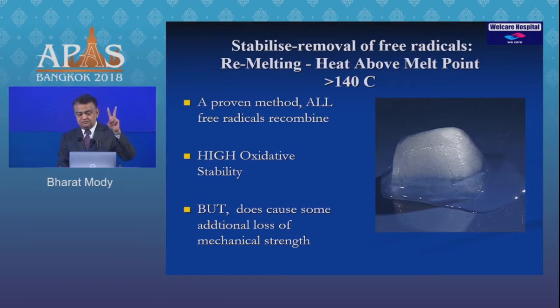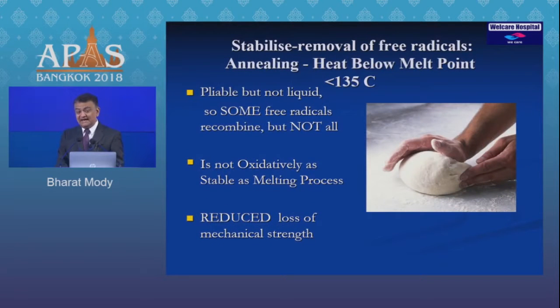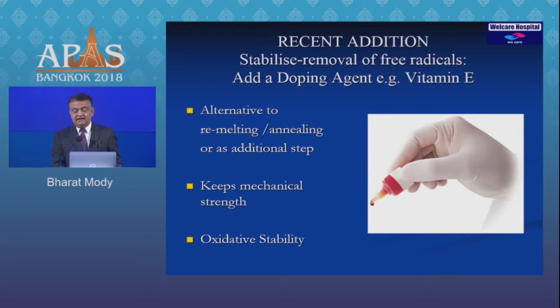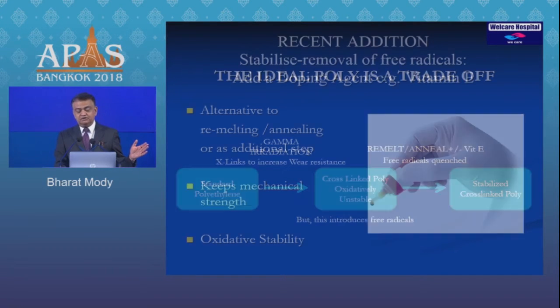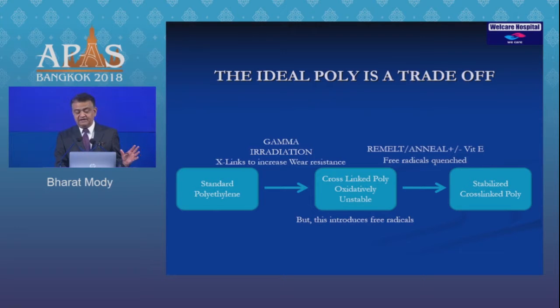And there are two thermal processes. One is remelting, which means melting it above the melt point of poly. This removes all free radicals and makes it highly stable oxidatively. But once again, it causes some additional loss of mechanical strength. The other method is called annealing. Annealing is when you raise the temperature but keep it just below the melting point, you make the poly into a doughy substance. This takes away free radicals, but not all of them. So whilst it improves the oxidative stability, it reduces the loss of mechanical strength. And lastly, you have the additive of antioxidants these days, like vitamin E, which is an alternative to the thermal processes. So in other words, ideal poly is a trade-off.